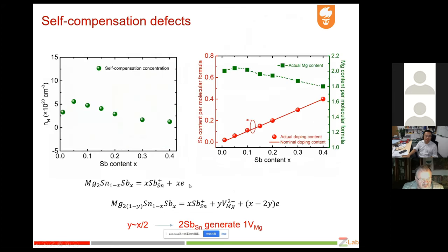We have more evidence for the existence of the magnesium vacancy. Here we measured the carrier concentration by the Hall coefficient measurement. You can see at low antimony doping content, the carrier concentration slightly increases and reaches a saturated value. Then the carrier concentration declines with the increase in antimony content. This is due to the vacancies, which contribute extra holes that cancel out the majority carrier concentration. At the same time, we also measured the composition using EPMA. We see that the real magnesium content deviates from the stoichiometric ratio.